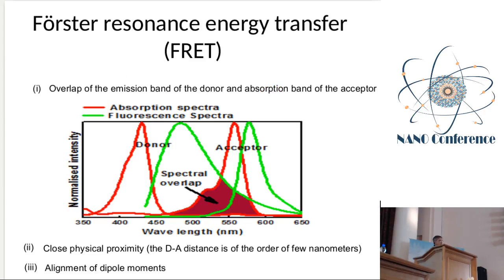There are a few conditions for efficient energy transfer in the Forster resonance process. The first condition is the overlap of the emission band of the donor and the absorption band of the acceptor. The second condition is the close physical proximity, the donor-acceptor distance between the players of this process. And the third condition is alignment of dipole moments. The dipoles should be aligned in order to efficiently transfer the energy.